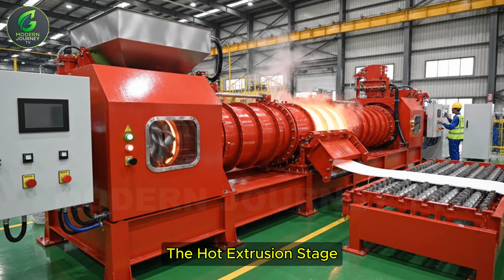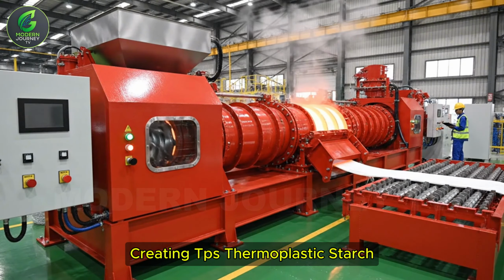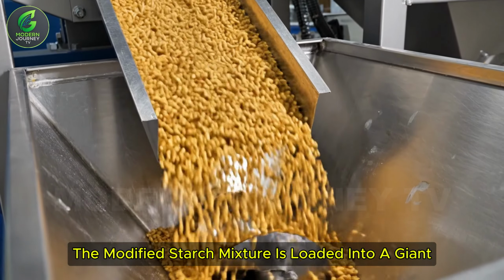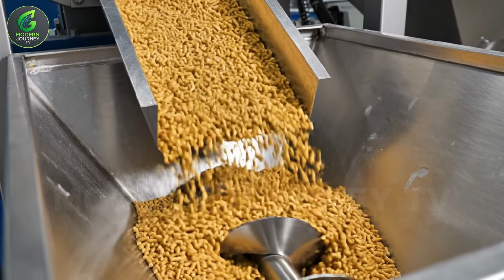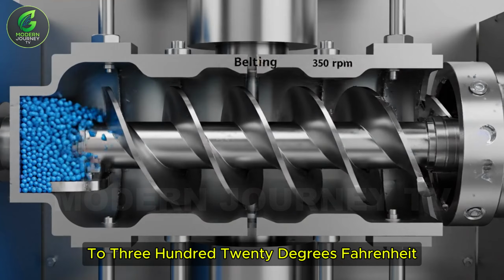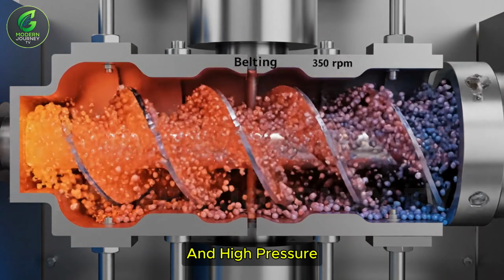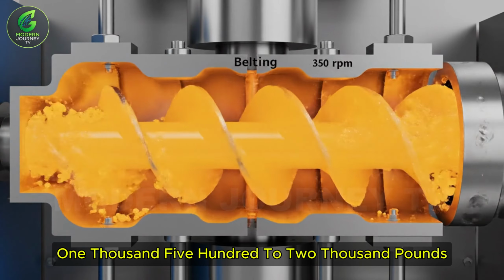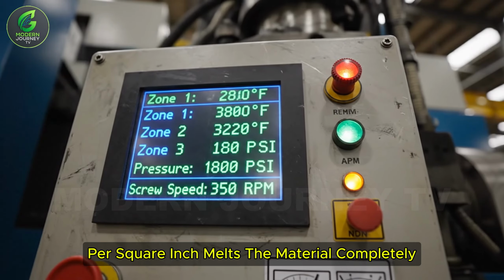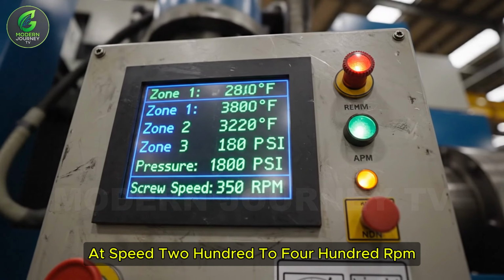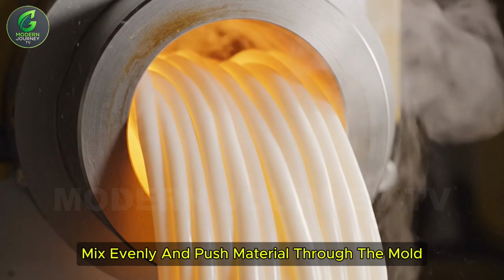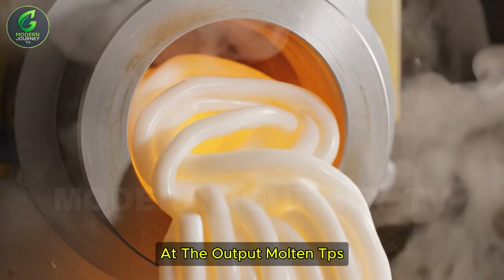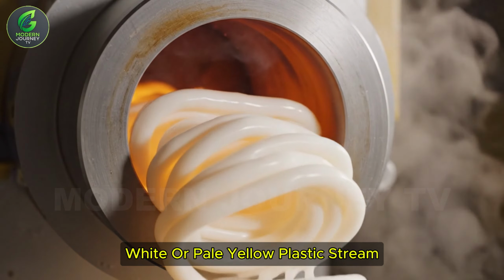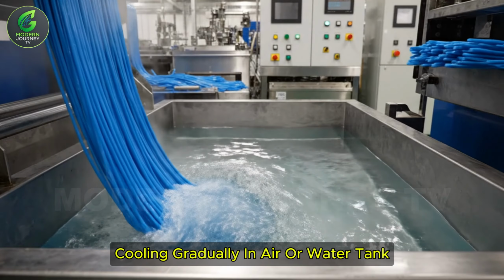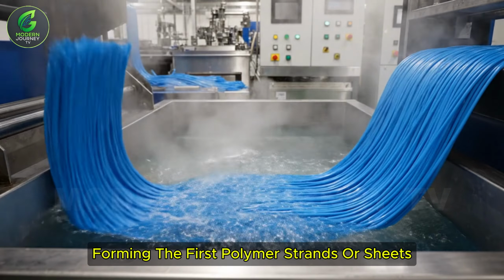The hot extrusion stage creating TPS thermoplastic starch. The modified starch mixture is loaded into a giant twin-screw extruder. Inside, temperature from 280 to 320 degrees Fahrenheit and high pressure 1,500 to 2,000 pounds per square inch melts the material completely. Two screw shafts rotating backward at speed 200 to 400 RPM mix evenly and push material through the mold at the output. Molten TPS flows out like ivory white or pale yellow plastic stream, cooling gradually in air or water tank, forming the first polymer strands or sheets.